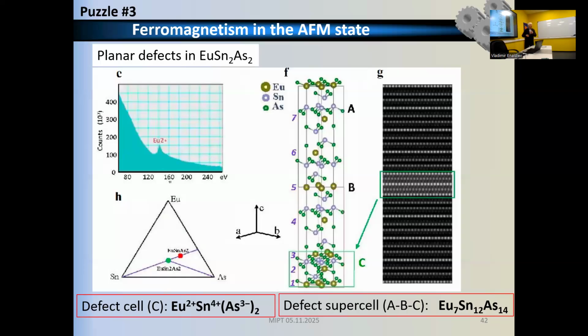And using all the power of machinery, crystallographers, my colleagues, managed to fit this. And it turns out that the minimal transition supercell layer consists of 33 atoms. And it slowly changes from regular to defect layer. And it has a general composition of europium 7, tin 12, and arsenide 14.